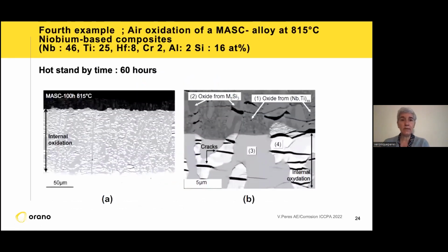The fourth sample is the oxidation of a MASC alloy. MASC alloys are niobium-based composites: 46 niobium, 25 titanium, 8 hafnium, 2 chromium, 2 aluminum, and 16 silicon. These alloys are very interesting because they are also composites with different phases inside. And when you oxidize under air and oxygen at high temperature, you have different behaviors.